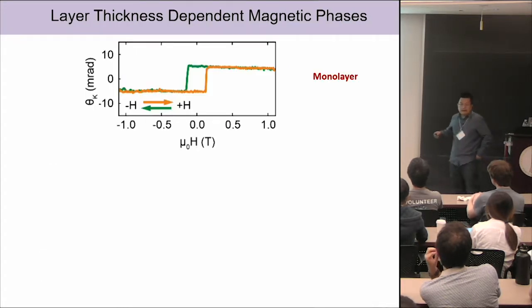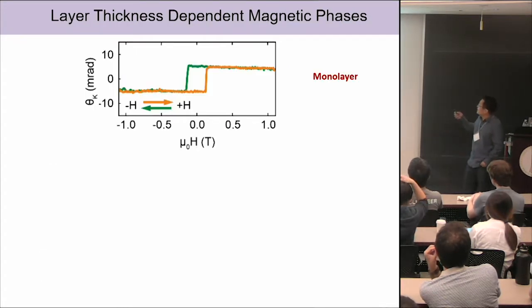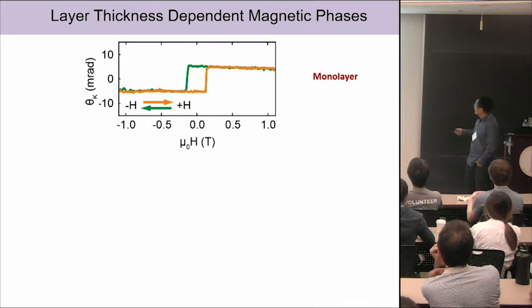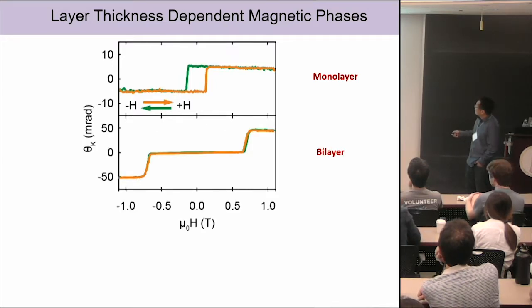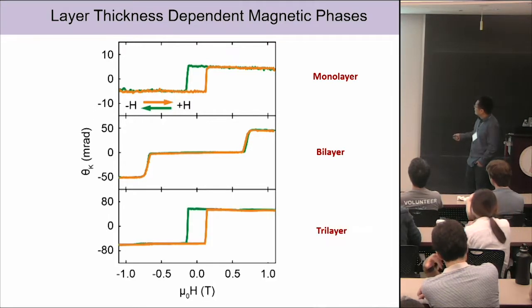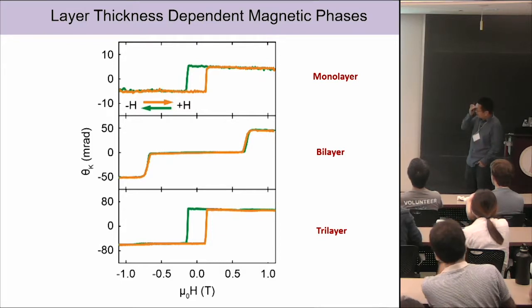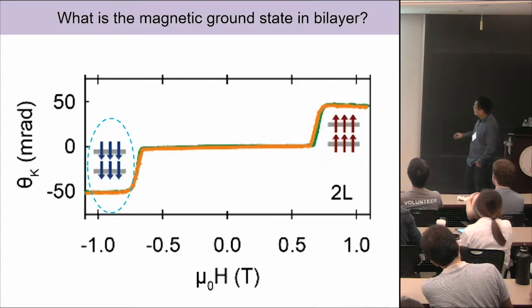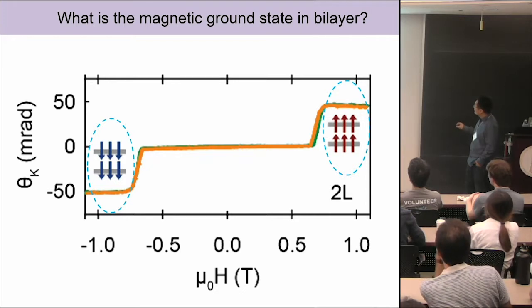What's really interesting in this system is that we have layer-dependent magnetic properties. For example, in the monolayer you already see this Kerr rotation, and there's a hysteresis. When you go to bilayer, the hysteresis vanishes, and the Kerr rotation signal also vanishes at small fields. If you go to trilayer, the signal comes back. Initially, we were puzzled by this for a long time. Then we realized it's caused by interlayer coupling.